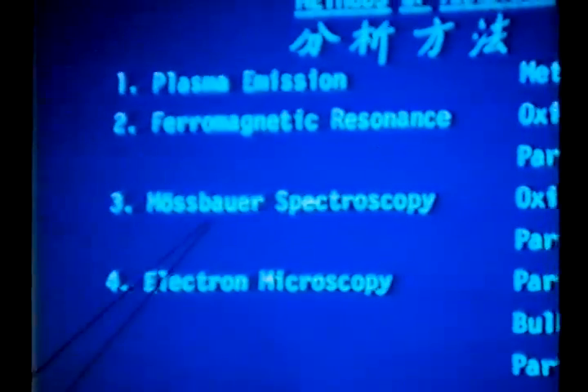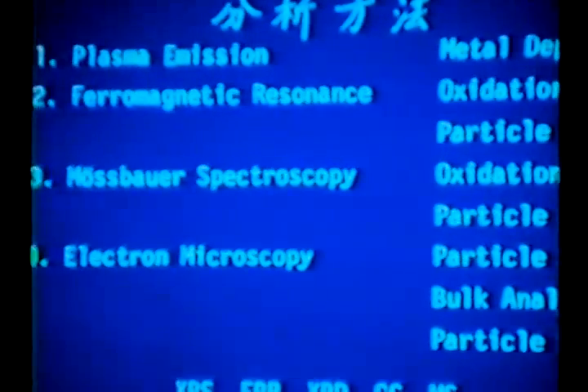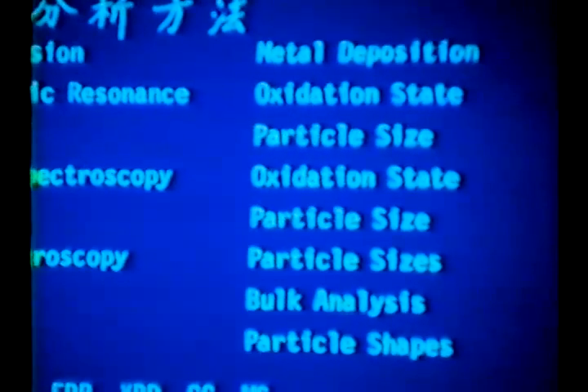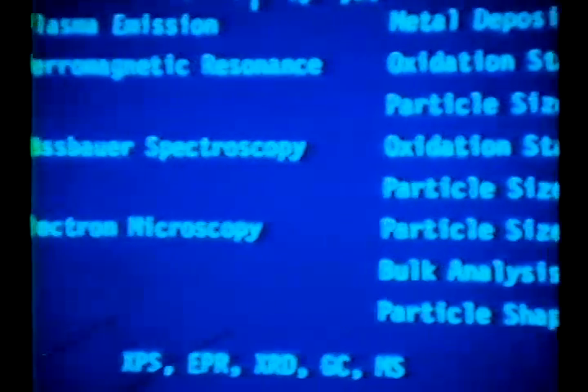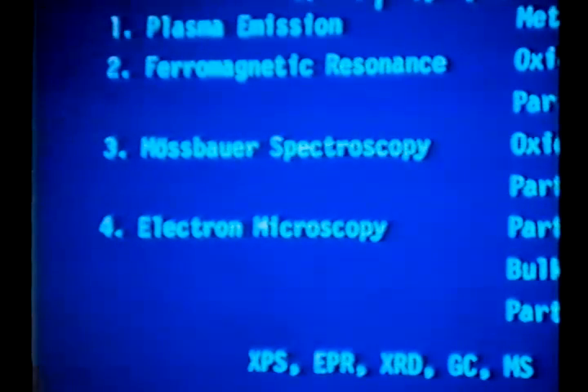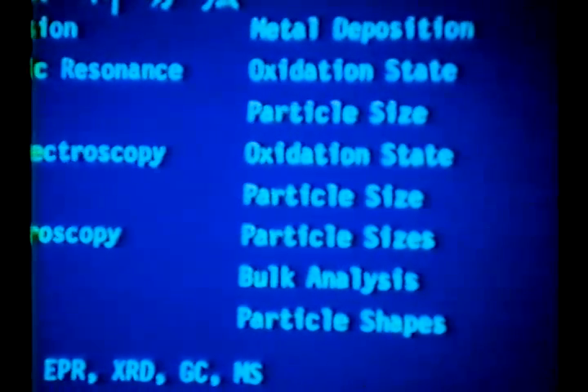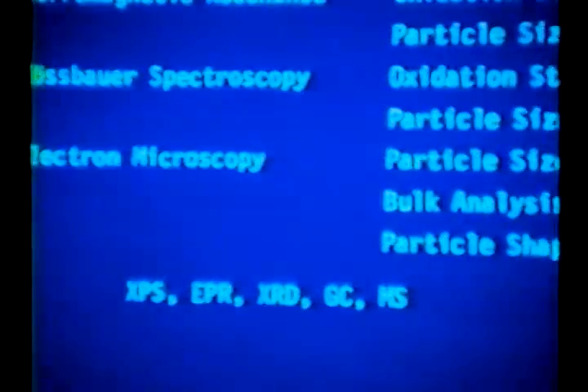I won't show any Mossbauer spectroscopy because you might laugh at it from your experience. Well, it's what the real story is with the iron materials. I should tell you this because this is important to the story. I'm only going to talk about cobalt because we finally were able to make these small iron particles, but they carbide just like large iron particles, so they're not extremely useful in terms of catalysis.